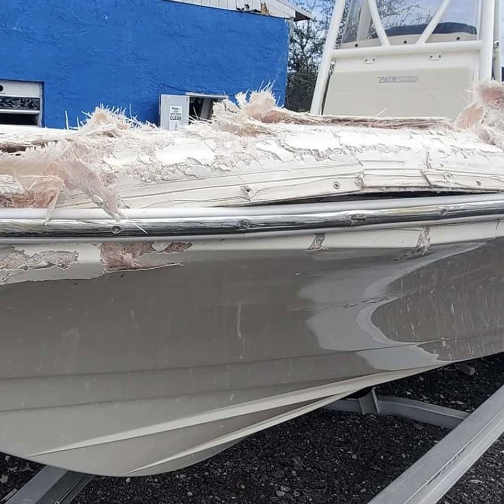If it's in a gunnel or something like that, maybe you've already had an opportunity to measure how much glass you need to add. So you've got an idea how many layers you want to put in beforehand. One thing that you can do is do a little test laminate of your proposed layup schedule into the repair. And if you lay it up and trim it and then measure it, and it's the same thickness that you get when you span across your bevel area and measure underneath it, then you know that's the right amount of glass. So little things that you do like that can save you time, and not putting an extra layer of 1708 versus grinding off a whole layer of 1708, it's nice to not have to do that, especially if you can just take a little bit more time and really try to figure out how much glass you actually need.